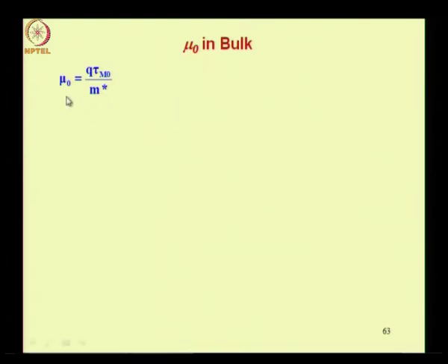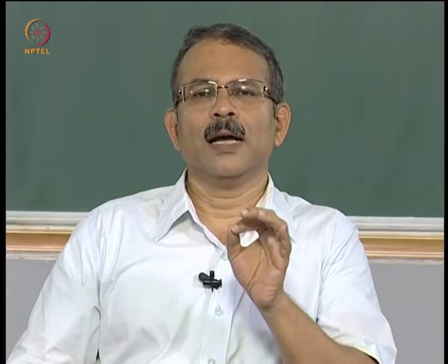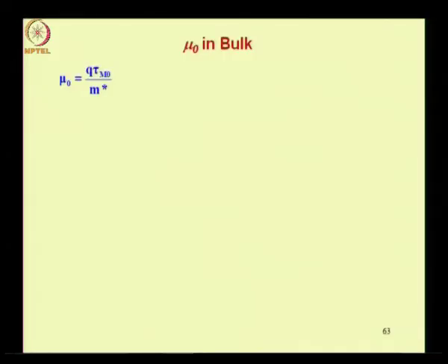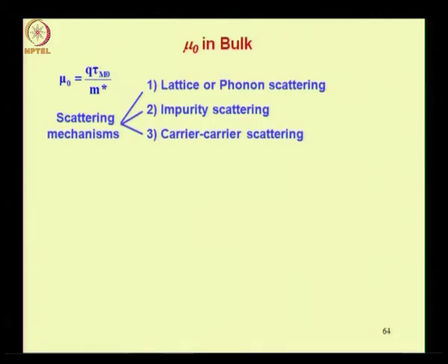The formula for mobility we are rewriting here from our earlier module. The low field mobility mu naught is equal to q times the momentum relaxation time close to equilibrium divided by the effective mass. Now we have said that we use the symbol m star when we want to generally refer to electrons and holes. If you are talking about electrons specifically, we will replace m star by m suffix n, and if it is holes it is m suffix p. The scattering mechanisms which affect this mobility are lattice or phonon scattering, the impurity scattering and carrier-carrier scattering. We have pointed this out earlier.